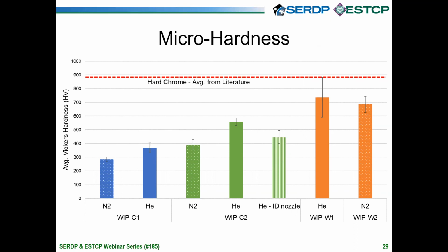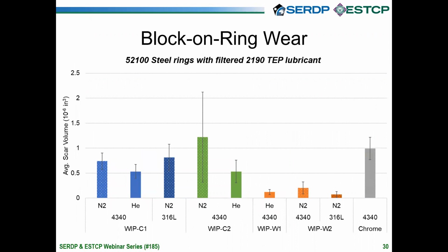Unfortunately, none of our coatings had equal or better hardness as typical chrome plating values, but the W1 and W2 coatings do come close in hardness. However, we don't see this as being a disqualification of cold spray because hardness isn't the only metric that is important. And in fact, we found that in many cases, our cold spray coatings have better wear protection than chrome plating. So that brings us to the next slide.